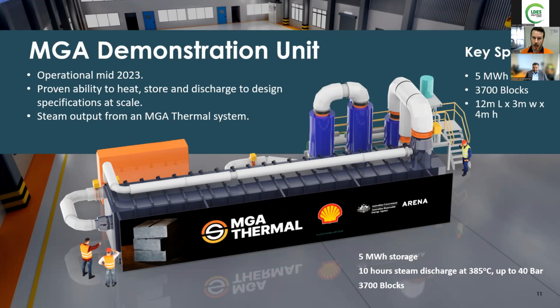It's charged up using 0.5 megawatt of electricity, which currently is over the grid, but will very shortly actually be coming from a rooftop solar system on the roof of our factory. It stores 5 megawatt hours of thermal energy, and then it discharges, in this case, to moderate temperature steam at 385 Celsius, 40 bar. And we can discharge that at capacity for a 10-hour period. So that gives us our 5 megawatt hours of storage capacity. And that corresponds to about 3,700 of our blocks. So it's about 4 days of manufacture for us to populate this unit.